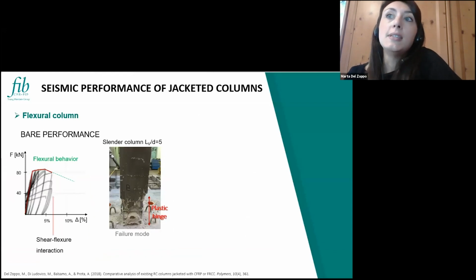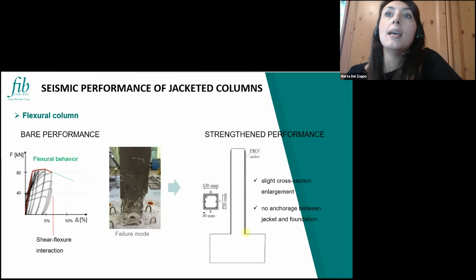So this is the first application, and this is on a slender column that is governed by a flexural failure mode. During the test, the column developed flexural behavior, achieved the maximum bending capacity, and then showed a sudden drop in the lateral strength caused by this shear flexure interaction. Of course, this shear interaction limited the ductility of the specimen. And the same specimen, without any damage, has been strengthened with the technique that I discussed previously.